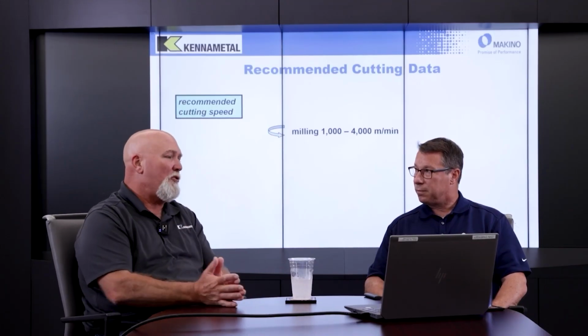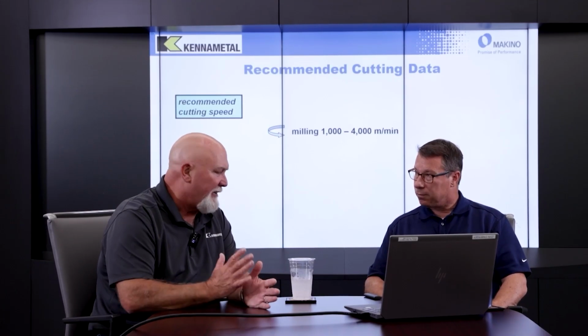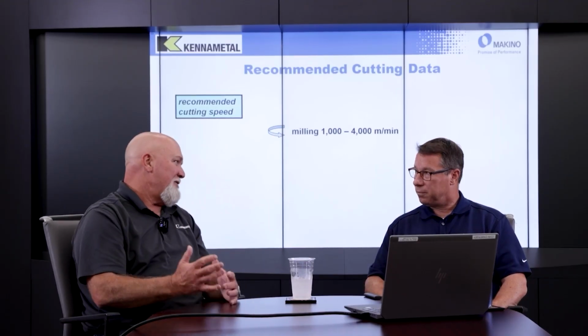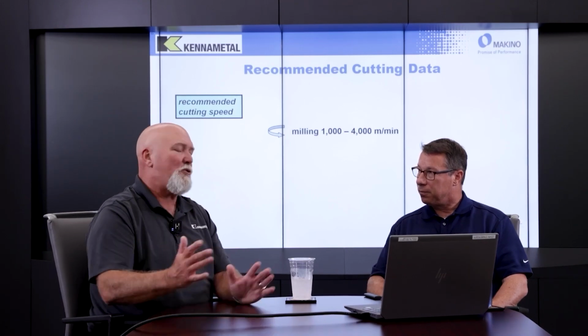So in the one that I was involved in, we had to run a really low speed to get through that. The ceramic particles in the scale was microchipping the diamond. So we slowed the speed down and was able to get through it there. And that's where the range can help you.